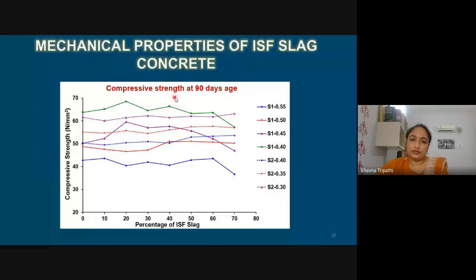The 90-day compressive strength is also similar. It is now more clear that the difference between ISF slag concrete mixes and those of the control mixes is very marginal. So from compressive strength point of view, we can clearly say that up to 70% also we can use, except for this mix, which is at the highest water cement ratio. This is showing a little bit of dip in the compressive strength. Otherwise, all of the mixes are showing, as compared to control, there may be appreciable increase in compressive strength, but what we are concerned with is how much decrease we are observing. So the decrement is marginal, and which supports the use up to 70%.